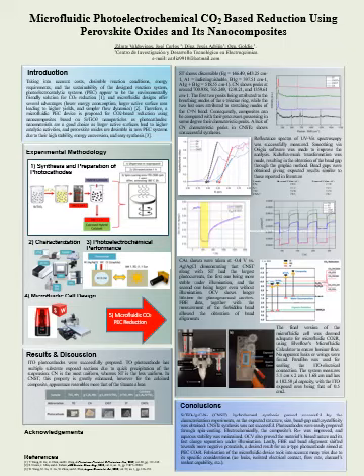In order to synthesize the graphitic carbon nitride with strontium titanate, hydrothermal synthesis was done, starting from both precursors. 20% graphitic carbon nitride was placed with strontium titanate, and following hydrothermal synthesis, the reaction was performed.